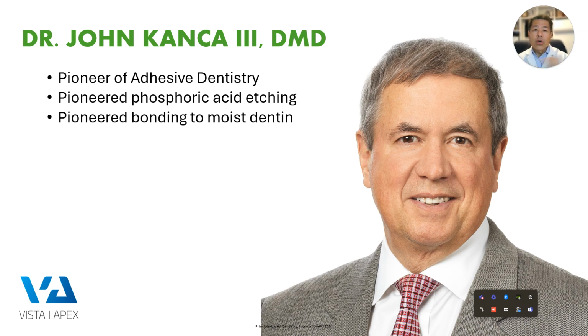Then once we did our etching, we were told when I was in dental school to rinse off that etchant and to dry that tooth, get the enamel bone dry. You want to see that frosty ring of enamel, and of course you were drying the dentin that was right next to it. What Dr. Kanca said was, we're doing it all wrong. What we need to do is leave the dentin moist, not puddled wet, but moist, because then the solvents that are attracted by that moisture would pull our resins down into those dental tubules, and we would get a better, stronger bond and seal those tubules up better, which would then mean less sensitivity and a healthier tooth in the long run.